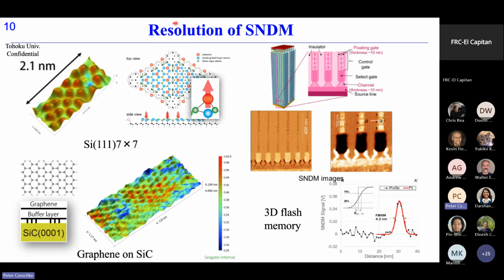And also, when we measure the semiconductor material and device, for example, when we measure the silicon 111 7x7 atomic structure, we can measure the atomic dipole moment of the surface. In this case, the measurement was done in the ultra-high vacuum circumstance, and also SNDM is operated in non-contact mode. And also, this is graphene on a silicon carbide substrate. You can see this very tiny hexagon is the benzene, actual benzene structure of the graphene.